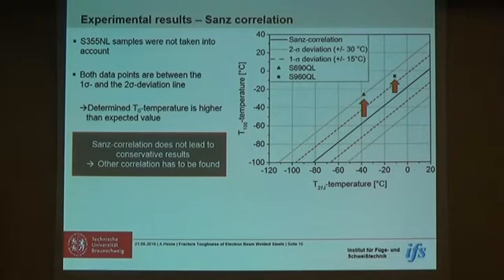If we look at our results in terms of the Sanz correlation, we have here the T27 joule temperature and the T100 temperature in our diagram. This dark gray line shows the Sanz correlation, and that should be the line where we would expect our results to be if the Sanz correlation could be used for this kind of steels.